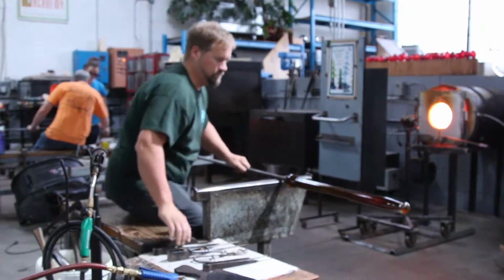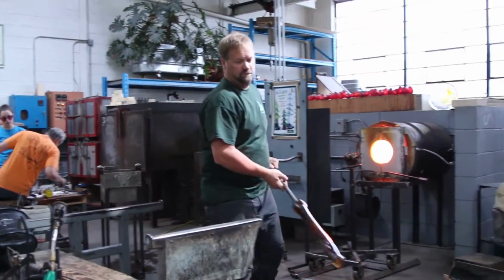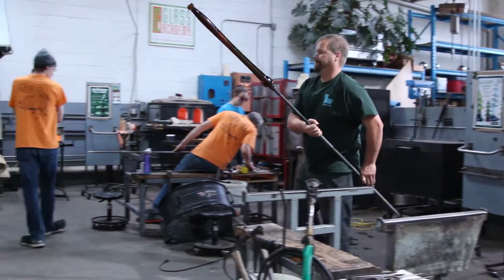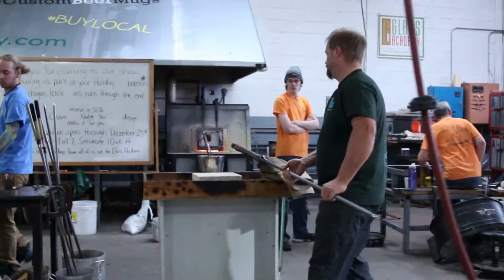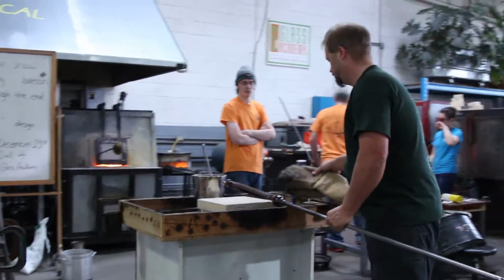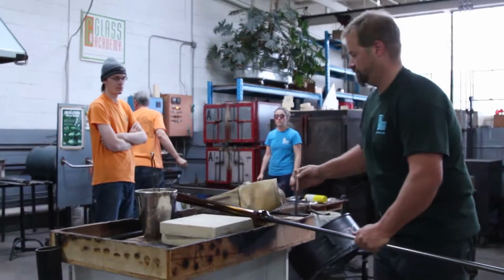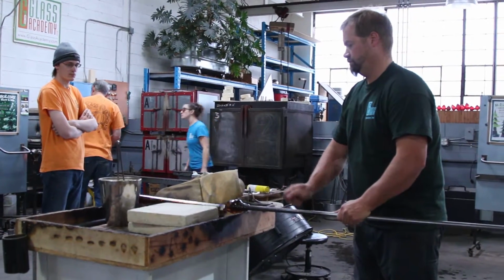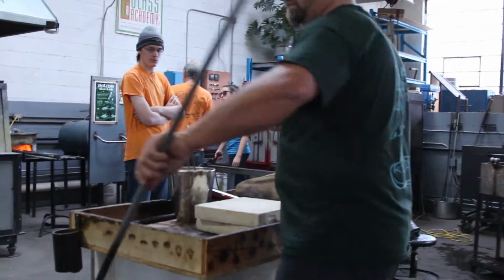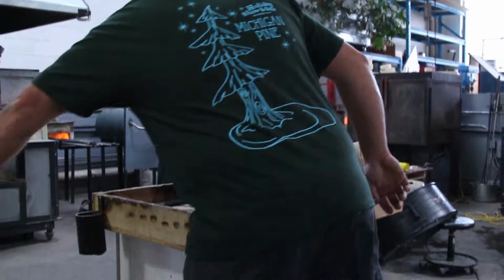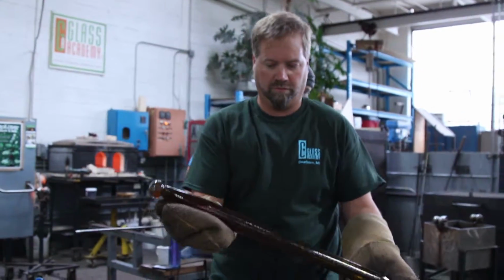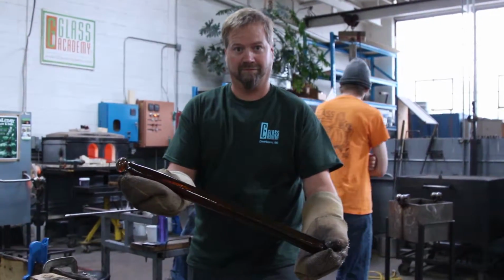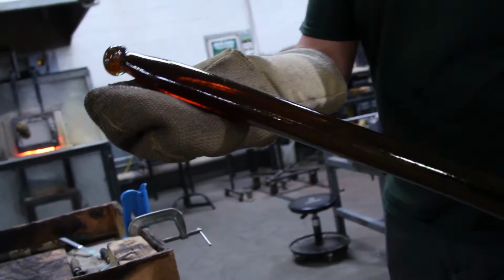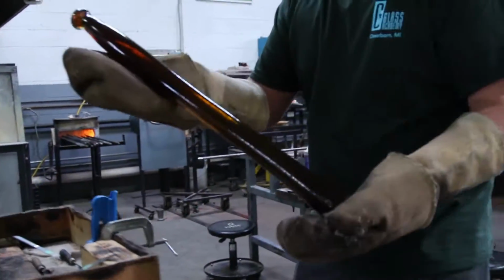The thicker the glass, the longer you have to anneal it, and I know that I'm going to be cold working and diamond sawing this particular glass, so I want to have it not have any stress in it, because when you're diamond sawing it, if there is stress, you'll get chips and shards that'll come off of it. So there's the finished piece right there, getting ready to go into the annealing oven, and we're going to get ready to start using the diamond saw a few days from now.